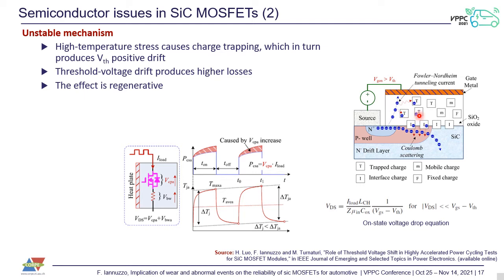This is a lot more likely to happen in silicon carbide than in silicon, because it is a wide bandgap semiconductor, and manufacturers, to hold the threshold voltage to a reasonably low value, have to fabricate the gate oxide with a reduced thickness compared to the silicon counterparts. When this happens, you have two concurrent phenomena. One is gate leakage current, so your gate driver is charged with active power. The other is charge trapping, which can last minutes, hours, or even days.